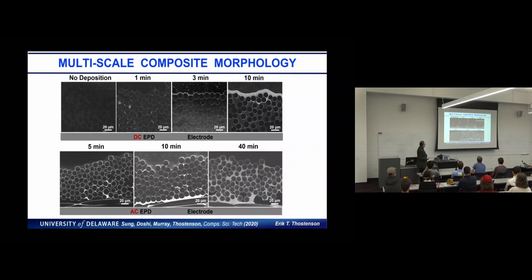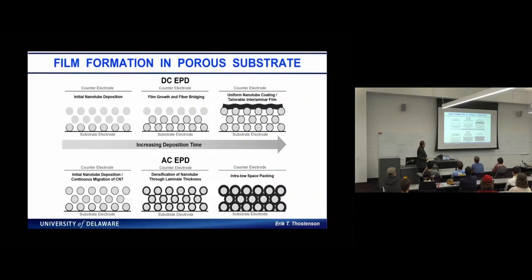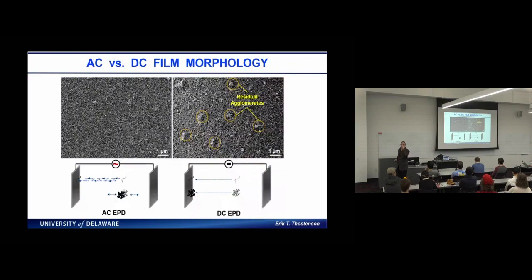This also shows some morphology under AC EPD, and for AC EPD, as I mentioned, is where we want to get more material in. So this is where we've deposited it, and you see these large regions of conducting materials. So that's just a highlight. We can control the morphology a lot by controlling the process and developing our process window.